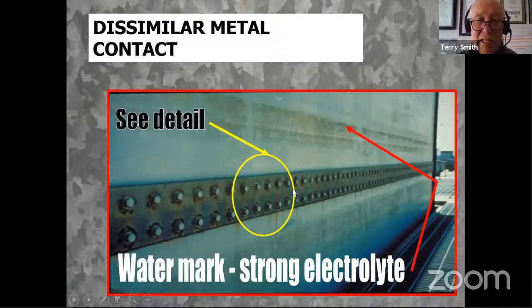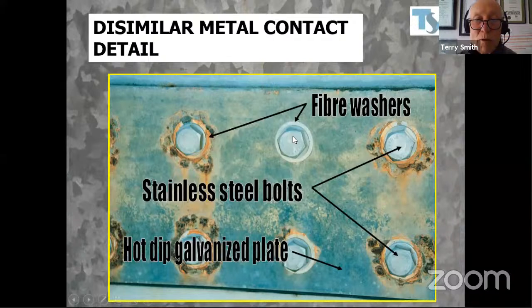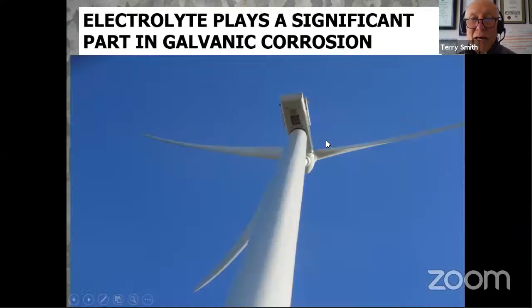This is a galvanized plate, and these are stainless steel bolts, and they used a fiber washer, assuming that it would exclude contact between the stainless steel and the galvanized plate. What they didn't realize is the bolts would not fit 100% in the center of the hole, except this one, which was in the center. All the others actually made contact on the inside, and you had corrosion of the zinc coating in this instance. So electrolyte plays a huge role.